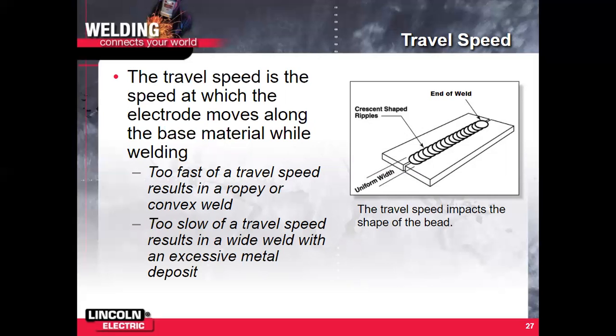The amount of weld, the size of weld, the quality of the weld, all depends on the travel speed. So if you are moving too fast, you're going to end up with a quite thin, narrow weld with a lot of V-shaped profile on it. It's not going to penetrate well. You may have undercut, you may have spattered slag. Generally, it's not going to be very visually appealing at all.